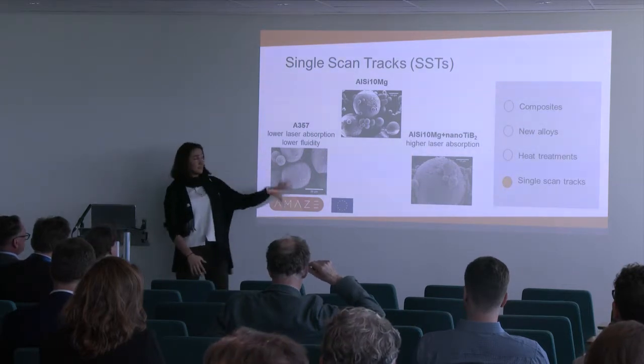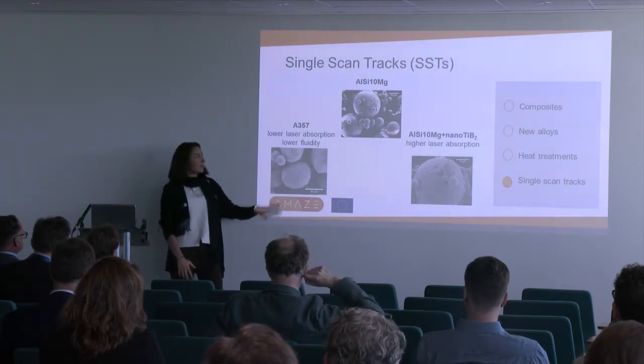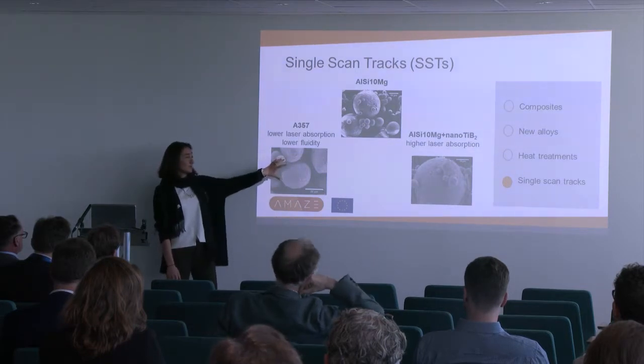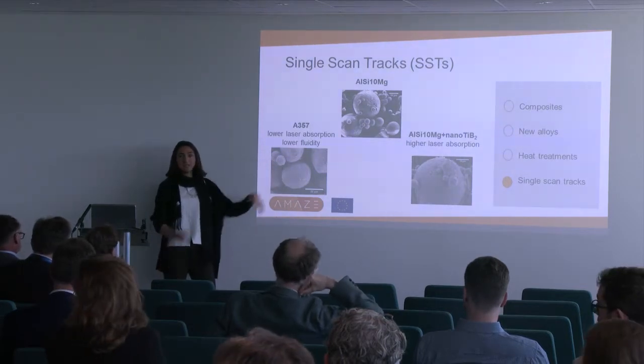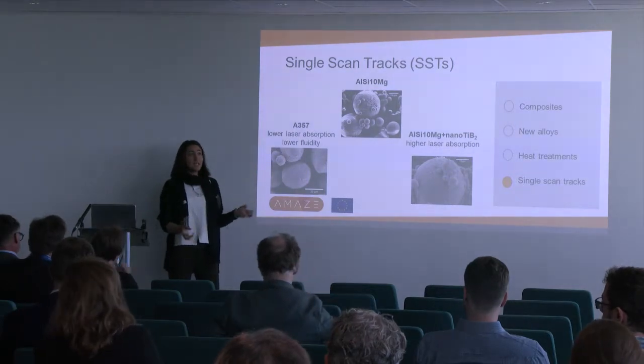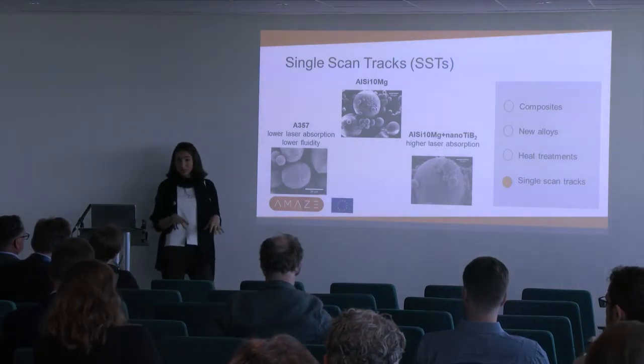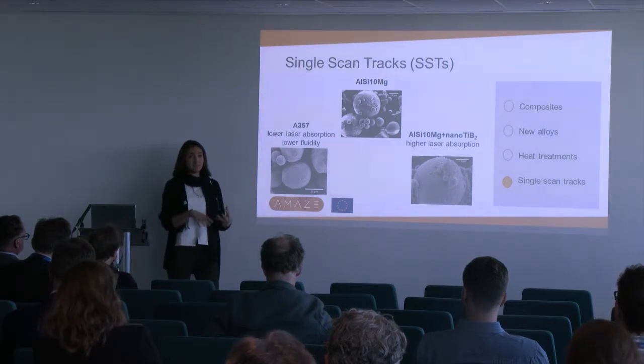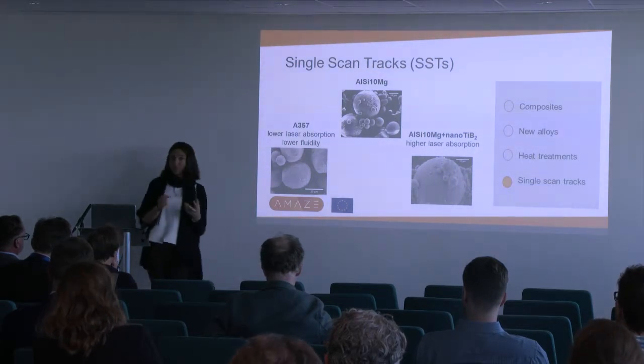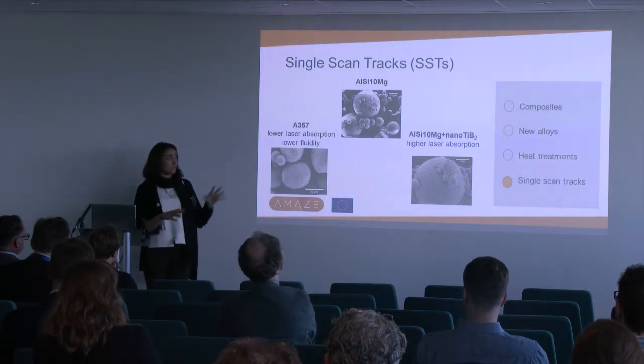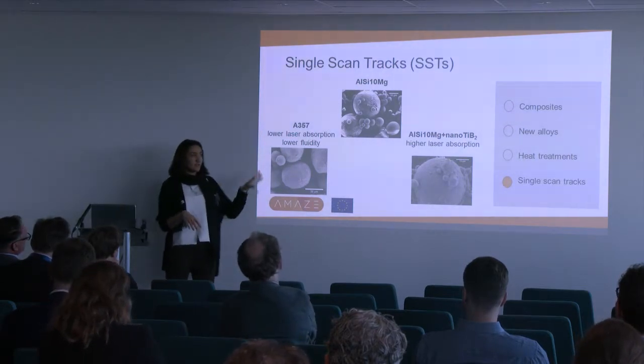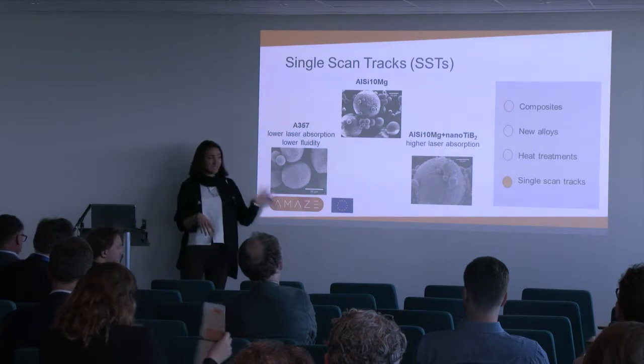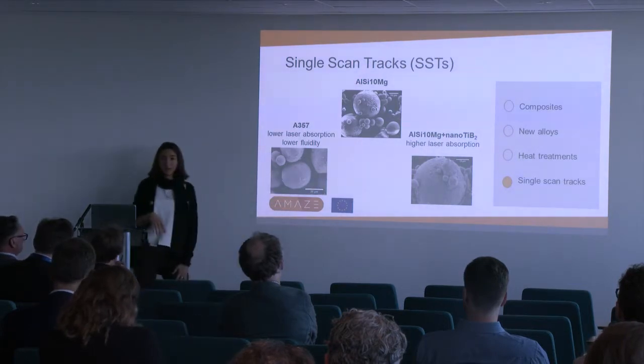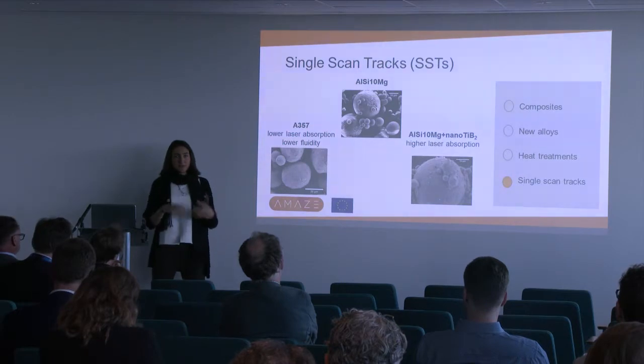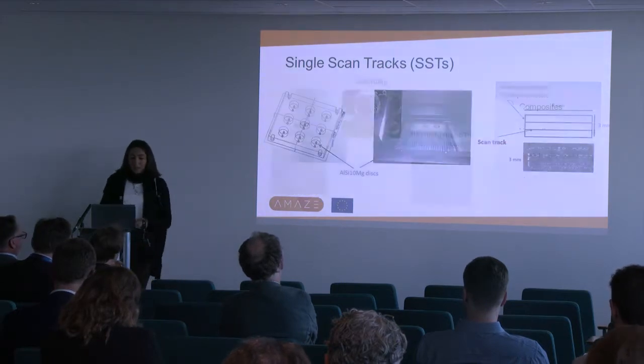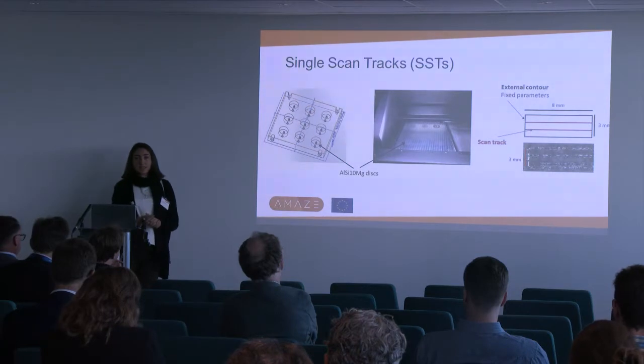The main difference between these three powders is that the powder which contains less silicon is less fluid in the molten state, obviously, and it probably also has a lower laser absorption, because the silicon is probably responsible for most of the laser absorption in aluminum silicon alloy. So it is less fluid and has less laser absorption, while the titanium diboride is a particle which absorbs most of the laser. So how did we do this single scan track?